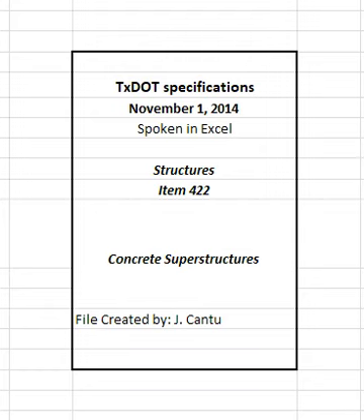4.1 Schedule restrictions and inspection hold points. 4.1.1 Placement of superstructure members. Place or cast superstructure members after the substructure concrete has attained a compressive strength of 3000 psi.